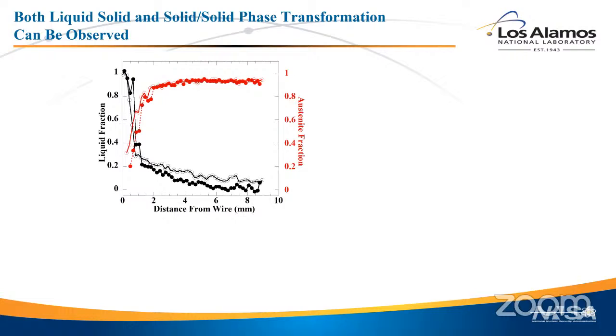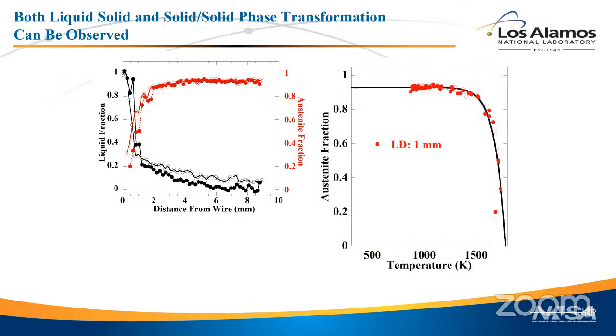you can then break the solid up into the amount that's ferrite, the amount that's austenite. So this in red is the fraction of the stainless steel that's austenite. You see it goes, and it takes about 2 millimeters of travel from the melt pool until it's pretty much its steady state amount of austenite. In the end, you'll find there's about 4 or 5 or 6% ferrite in there. Now, how the austenite forms as a function of temperature, because we have both sets of data.